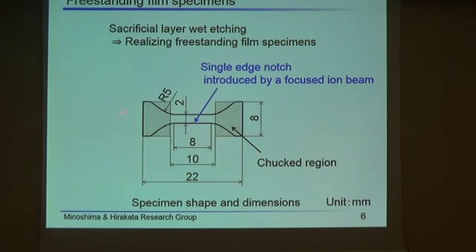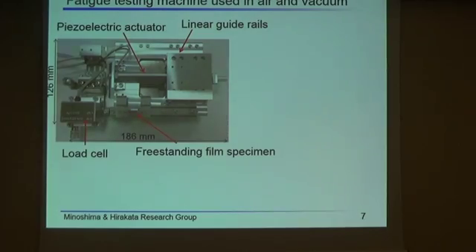This is the specimen shape and dimensions. We introduced a single-side edge notch as a crack starter into the specimen by using a focused ion beam. This is a fatigue testing machine used in air and vacuum. We employed a piezoelectric actuator and a load cell. This is a freestanding film specimen. The loading mechanisms are shown here.